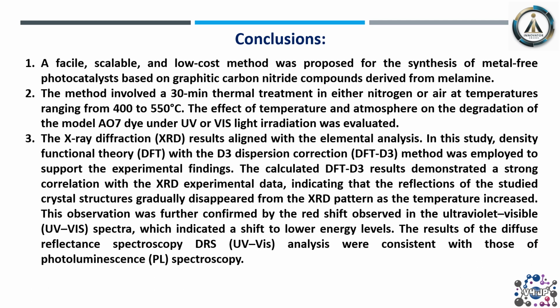The X-ray diffraction results aligned with the elemental analysis. In this study, also the density functional theory with the D3 dispersion correction method was employed to support the experimental findings, and the calculated DFT-D3 results demonstrated a strong correlation with the XRD experimental data, indicating that the reflections of the studied crystal structure gradually disappeared from the XRD pattern as the temperature increased.